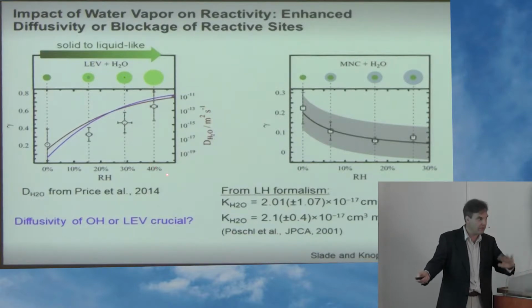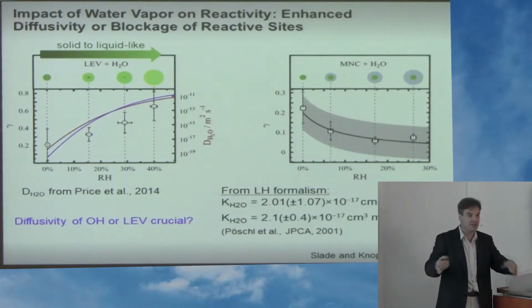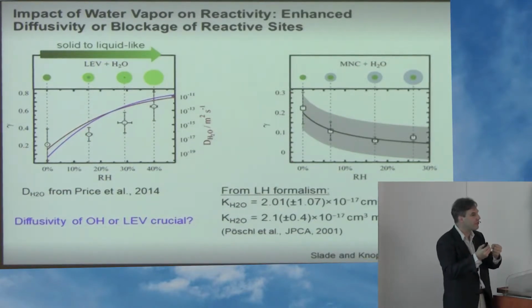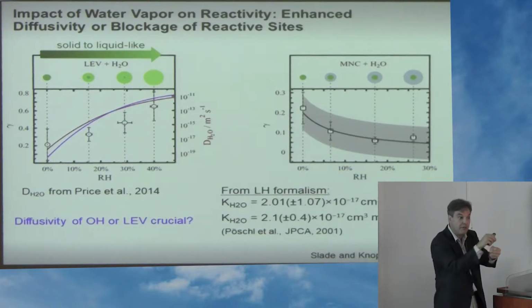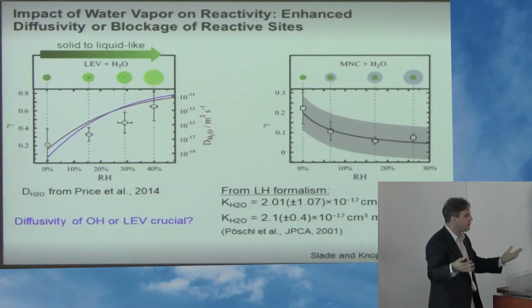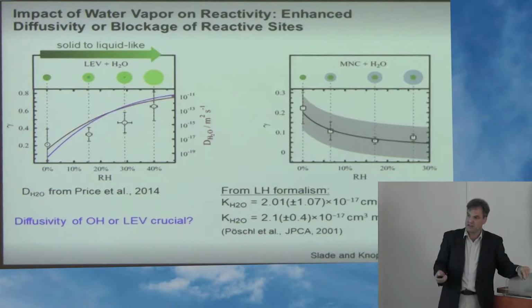We couldn't do more than 40%, it doesn't work with the experiment, and we see almost a 3-fold increase in reactivity. Our suggestion was — and the Murray group in Leeds published diffusion coefficients of water in levoglucosan — that this material becomes softer. Because it's softer, OH can go deeper in and react more, so reactivity increases. We published that in GRL, but that's wrong, and I'll show that in the next slide.